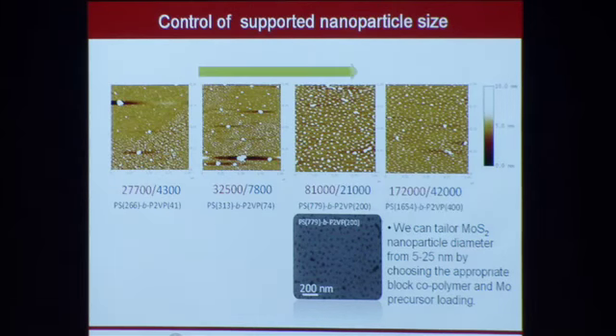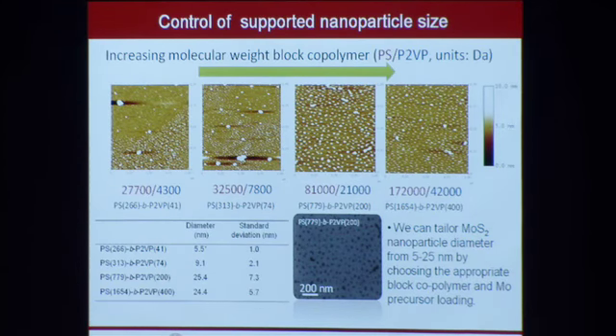So now that we have this method down pat, what we've done is we're changing the block copolymer. That's one of the convenient points of the synthesis. By changing the chain length of the polystyrene tail versus the polyvinyl pyridine head, and by changing the loading ratio of how much metal we dissolve in our solution, we can get changes in the nanoparticle size.